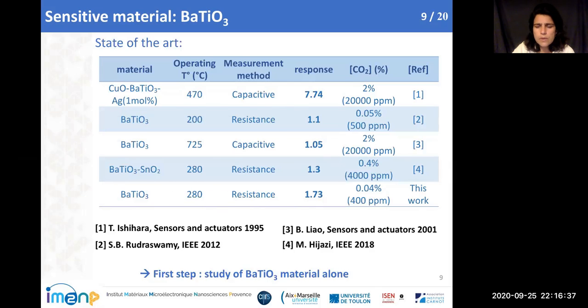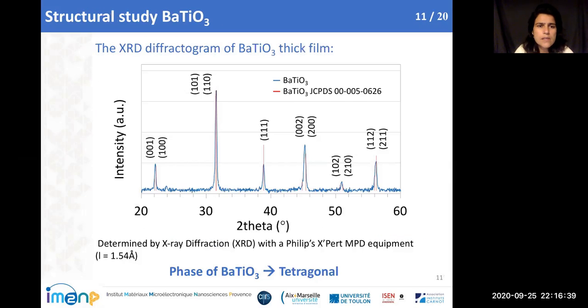After that, we make an XRD diffractogram, and we obtain different peaks. So we have a crystalline thick film. And if we compare with the literature and reference values of these peaks, we can see that we have a tetragonal phase for this barium titanate thick film.